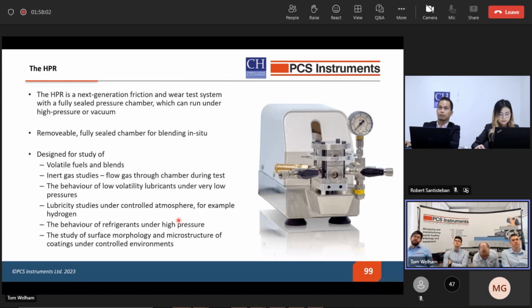The design of this allows for the removal of the chamber to maintain the pressure or vacuum even when it's off the system, so we can test blends to be made in situ. And this is combined with the low costs of standard specimens and small sample test volumes, which are really advantageous for the HPR. So it's a reliable and cheap way to test fuels and lubricants under different blanket environments, gases, or we can test volatile fuels and blends.